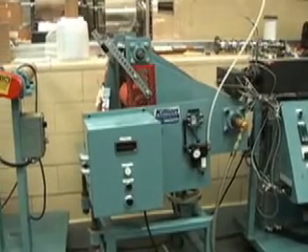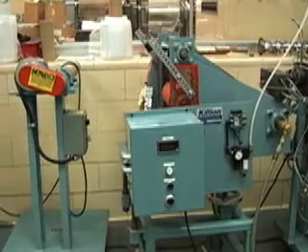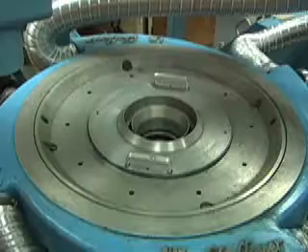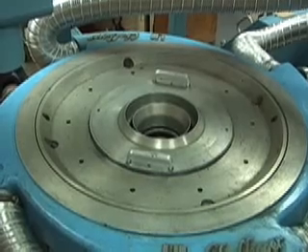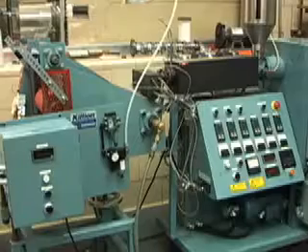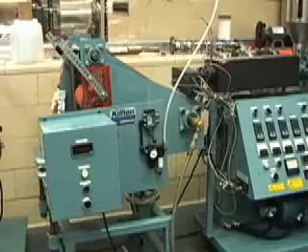The recently renovated extruder room houses both a cast film and pilot sized blown film line. The blown film line has a 2 inch ring die, 3 extruders, and is capable of making a 14 inch wide lay flat. The cast film line has a single extruder and an 8 inch wide die.